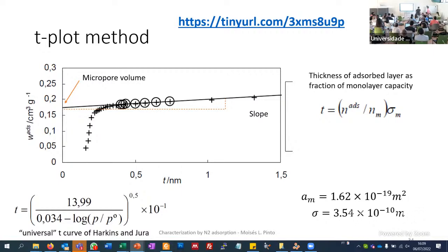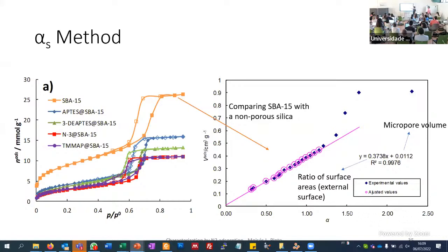And just to highlight here that there are other methods where you can compare, instead of a standard isotherm, with, for instance, a non-porous silica. In this case we are analyzing this porous silica, which is a mesoporous silica. What we are expecting is that if this is a mesoporous silica, then it should give 0 volume of micropores. And if you use the proper reference isotherm, you see, okay, close to 0, or very close to 0.